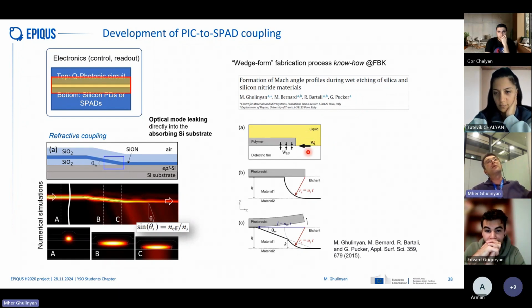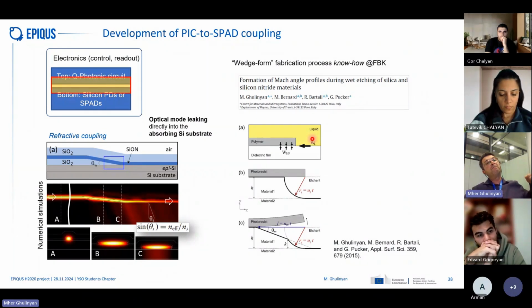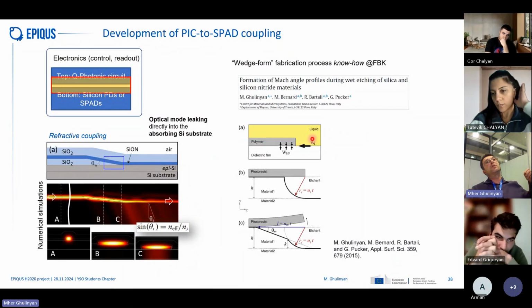Etching in general is removing part of your material. Okay, masking with something to protect it, and removing something that is not protected. So you can remove your material in different ways, like digging it with a very aggressive mode, for example, by bombarding with a plasma of ions like argon or other chemical gases that not only chemically react with your film, but they also mechanically bombard.